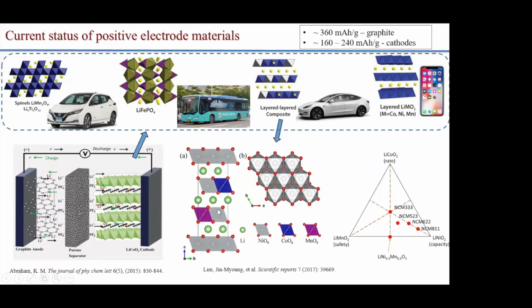And if you change that and bring in 2 cobalt and 2 manganese, then it will be 622 architecture. NCA is very similar, it's just that instead of manganese it has aluminum, but it's a very similar layered structure. And what we see in the iPhone is basically lithium cobalt oxide, a very similar layered structure too.